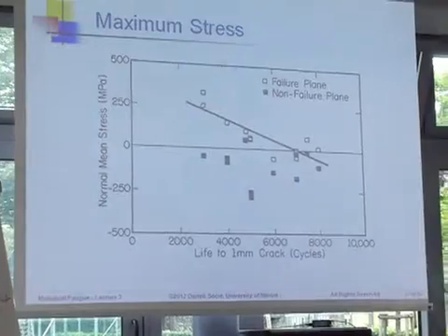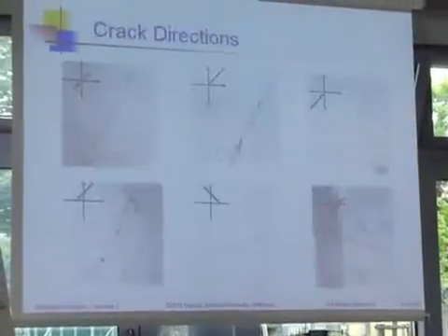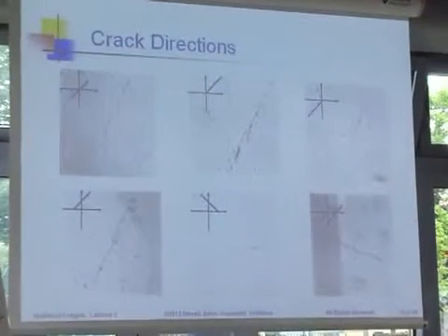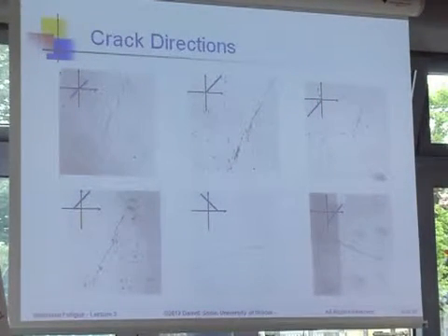And what happened was I could never in my mind predict what the stresses were. Never. I could say, here are the external loads and pull and twist and so on, but I could never predict what the ultimate stresses would be. As soon as I did all this plasticity modeling, so that I could calculate the stresses, then it was just clear. But only through the calculation of the stresses, because none of us can think in terms of those differential equations for the plasticity models. And so this convinced me that the stresses were, in fact, the most important thing, not the strains for the normal stress.